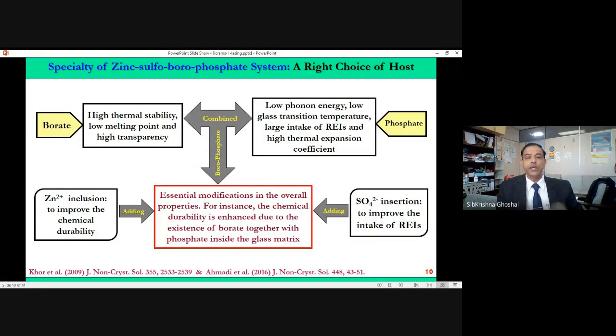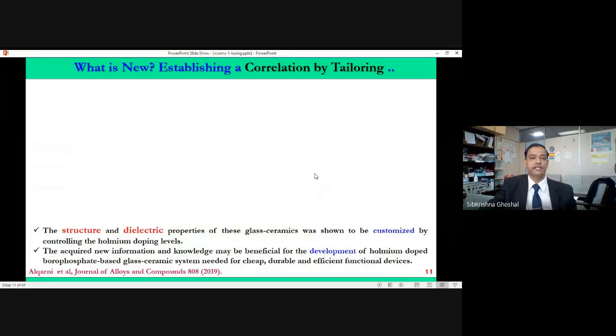Because in this functional glass, we entirely change the local potential. For the glass, the potential is already corrugated. And if you look at the free energy landscape, it is quite complicated. That's why glass is sometimes called a supercooled liquid or complex fluid. Even if we put some crystallites into this, the potential landscape becomes more complex. And controlling this potential landscape is really a difficulty. If you look at the Walter Kohn paper, which is called the nearsightedness effect, here we bring such a kind of effect in the potential well in the mixture of crystallinity and amorphous and tune the property of light emission. And that's where the complex and functional goal of material science starts.